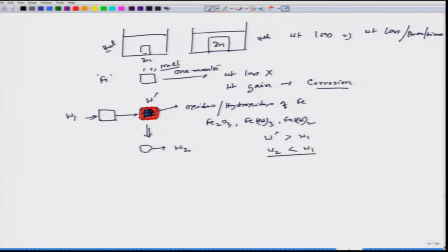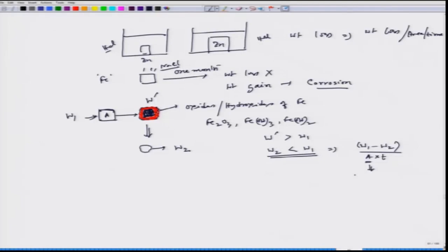So now we have to consider this one after removal of the oxide layer, and then we have to find out the corrosion rate. Now this area should be the area what was initially considered. Okay? So, the area of this particular block should be considered, because the dynamic change in area, it is very difficult to understand, because it may not happen completely uniformly. There could be some localized attack, or there could be some uniform attack. So, it is a mixture of things. So, that is what it is always better to consider the initial area in order to consider the corrosion rate. So, this should be my corrosion rate.